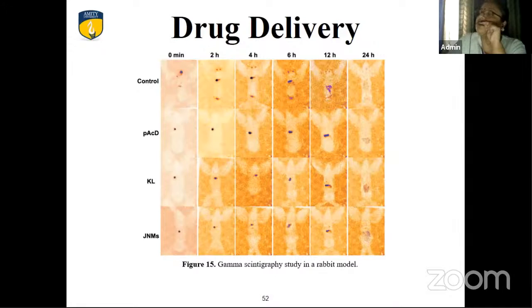then came down to some extent. As opposed to this PACD, the nanocomposites, that is the KL and Janus, exhibited an escalation in the residence time of the formulation, and Janus plausibly induced mucoadhesion, increasing the intestinal permeation of the drug, where the concentration gradient of 5-fluorouracil rises steeply in the large intestine, increasing the oral drug bioavailability. The on-demand release and high level of control supported by gamma scintigraphic studies reinforce our in vitro conclusion, proving their precisely predictable response with respect to stimuli.